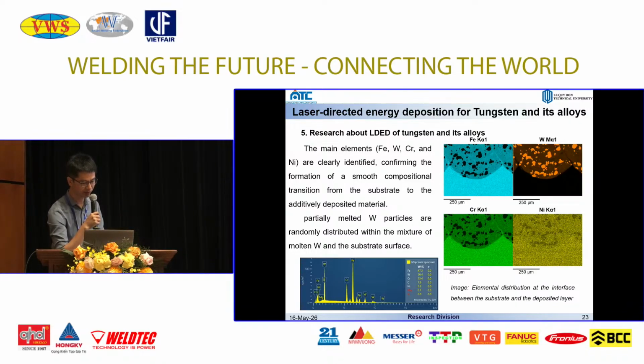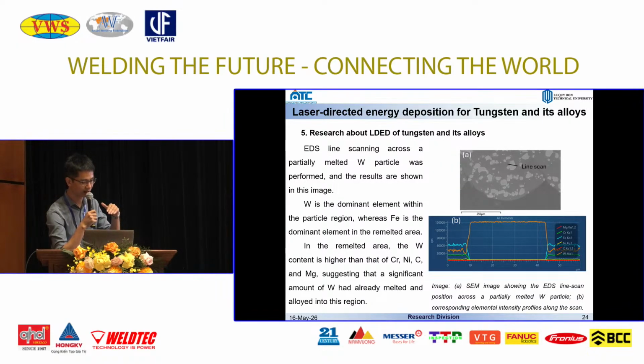Although some studies have identified such black particles as unmelted tungsten particles, depending on our observation, the more rounded morphology suggests that these particles were partially melted rather than retaining their original shapes. We also did an EDS line scan through a partially melted tungsten particle. In the center of the particle there is almost no iron, nickel, and chromium. It is only tungsten. But in this area, like a slope, that means at the boundary of the tungsten particle, it is partially melted and mixing with the base elements.